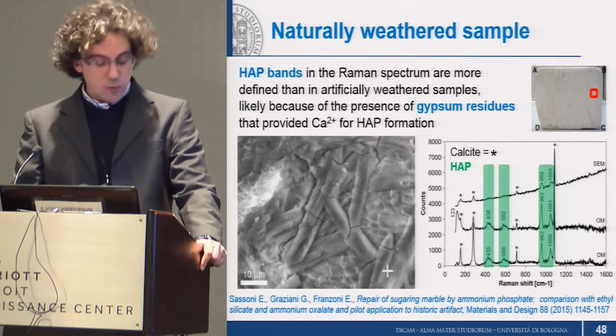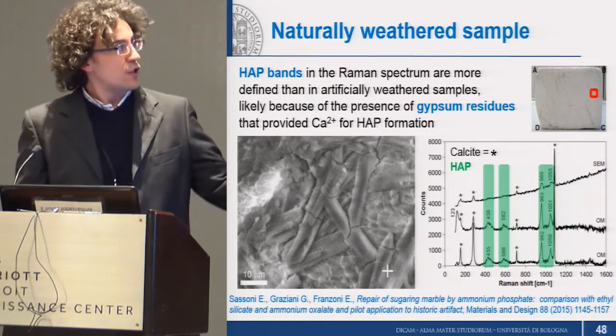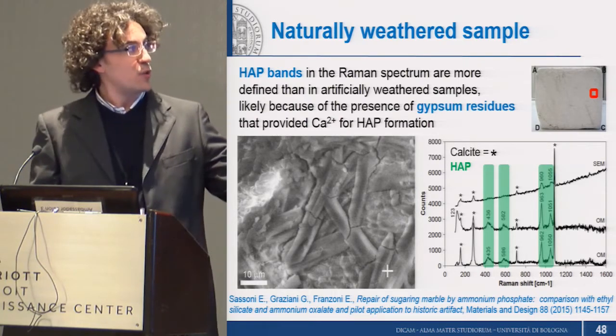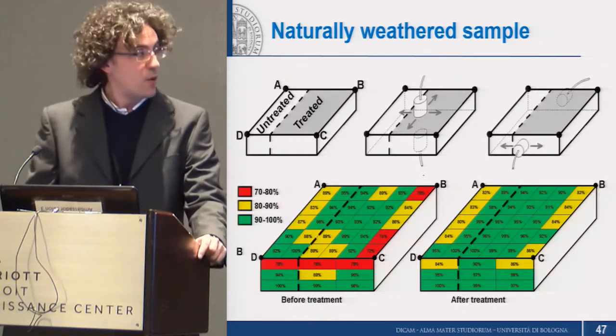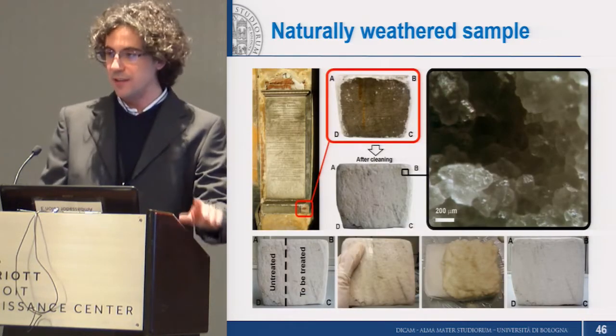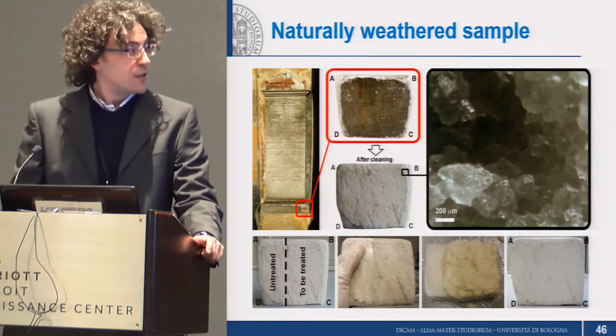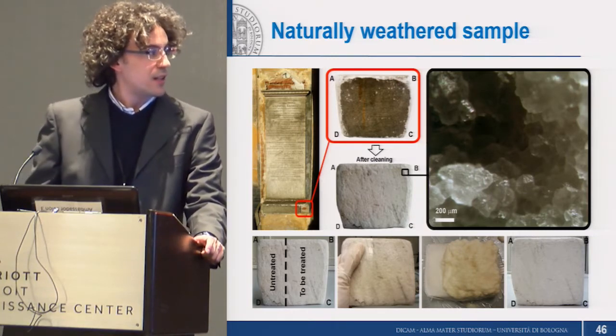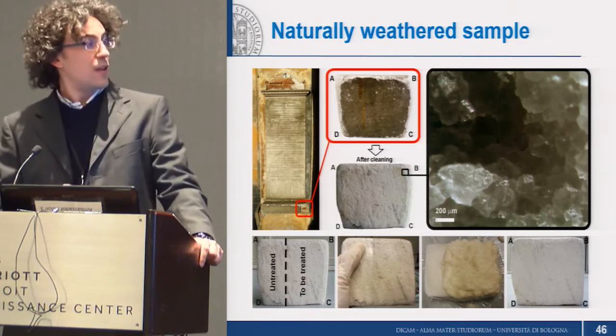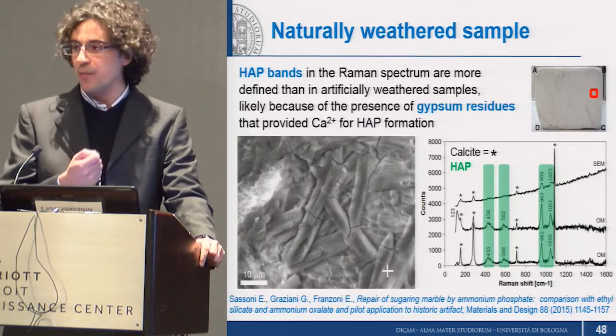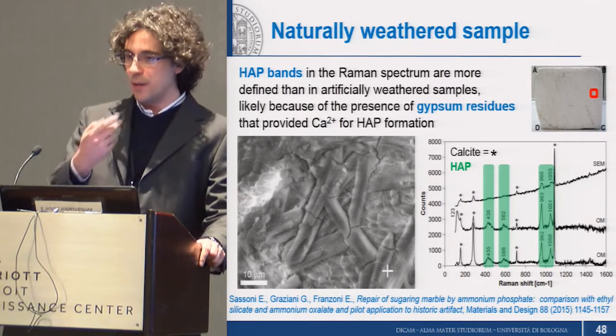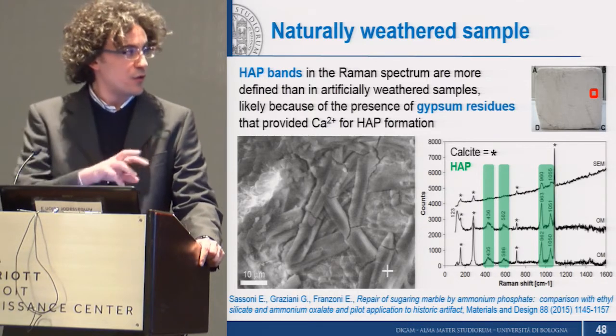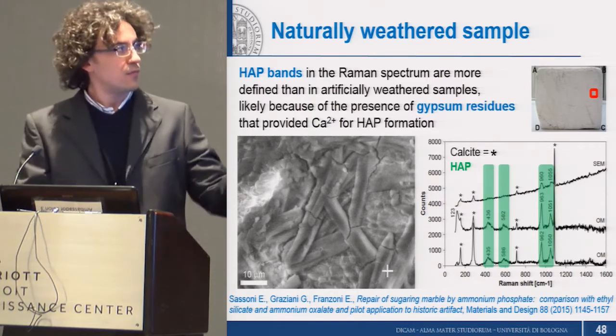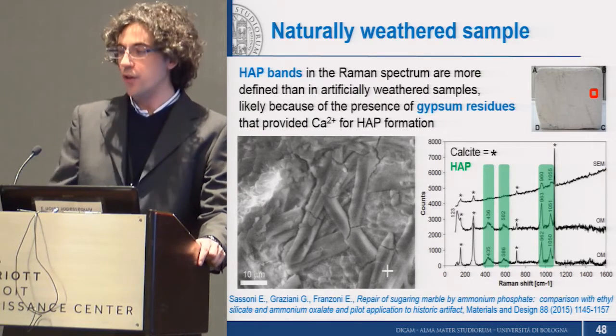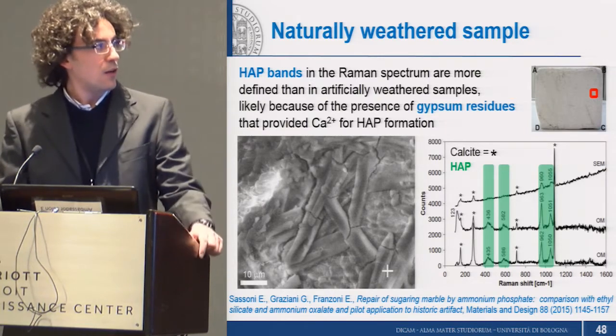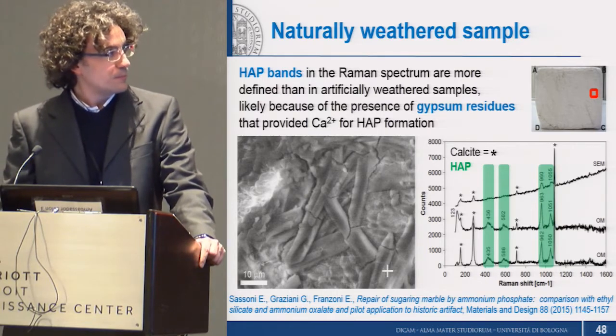And we think this is a consequence of the fact that a black crust made of gypsum was originally present on top of our samples. We carried out some cleaning, but still some gypsum, calcium sulfate hydrate, residues were still present on the surface. And because gypsum is much more soluble than calcite, it's able to provide some additional calcium ions for the reaction with the phosphate solution. And this proved to be beneficial for the formation of the new phases, so that only HAP was formed.